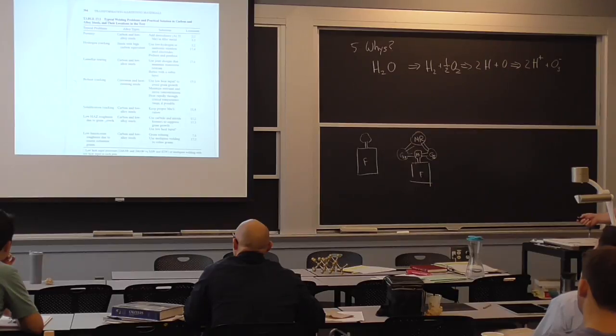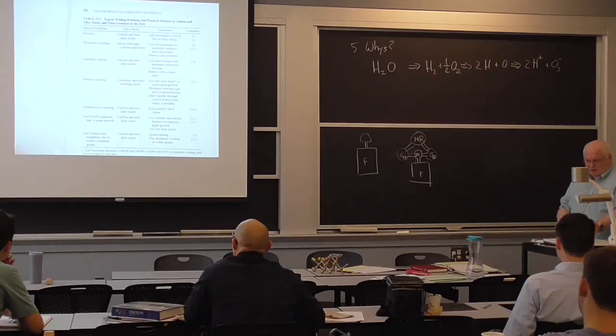Low heat affected zone toughness due to grain growth. Okay, let's talk about that for a second. Here's my HY80 weld from 30 years ago, made with an electric weld. And you can see the heat affected zone. See this little black region next to the fusion line?